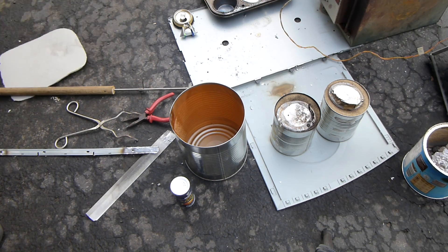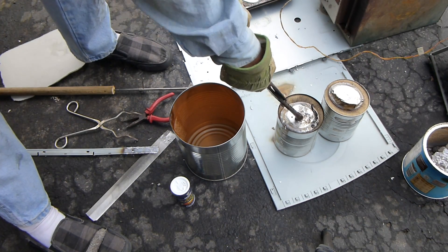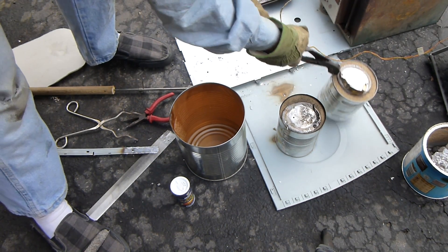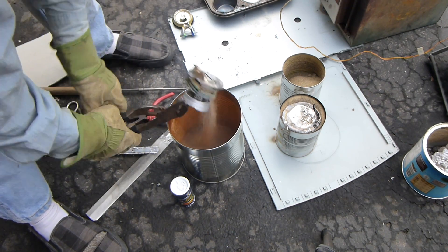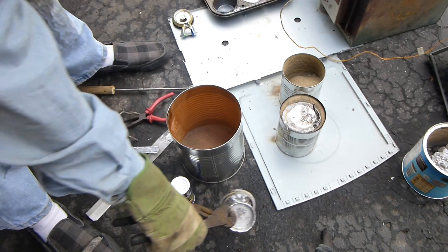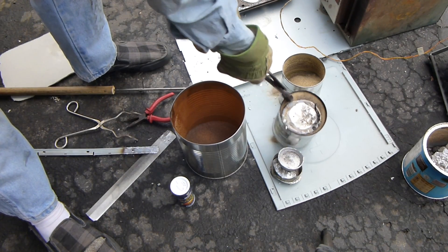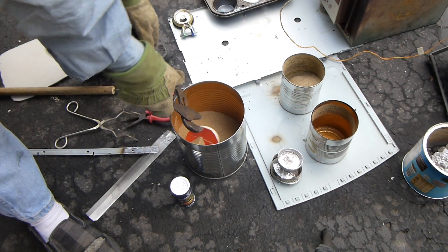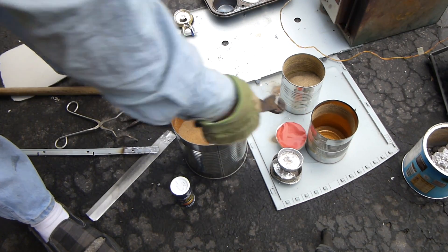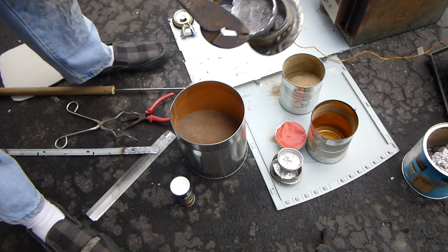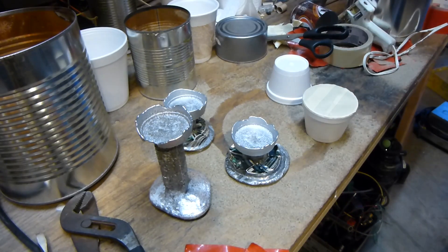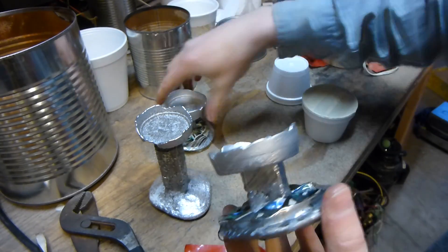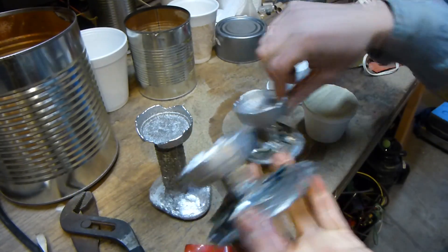Alright, now the moment of truth to see if these styrofoam cups are cast well out of aluminum. I'll do this one first, the one we did first. Well, it actually somewhat worked to a certain extent, not really, kind of, but not very well. So either the aluminum wasn't hot enough or it's just too thin and the aluminum cooled too quickly.